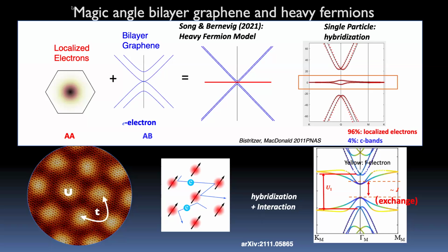Can I inject some healthy skepticism here, even though I like the model very much? If you make an estimate of U based on the dimensions of this Wannier state, and you put a huge amount of screening in, you get it down to 50 millivolts. But actually, the raw number is more like 100 millivolts, especially for your geometry. So there's a big difference between what you measure as U and what's predicted from the ab initio point of view. And I wonder whether you have thought about that.